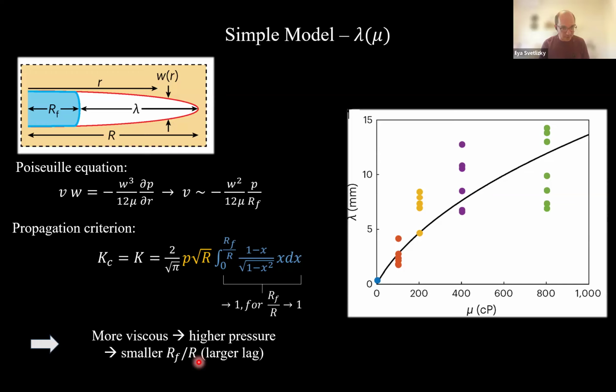This is absolutely right. The answer to that is that I'm cheating a bit, in the sense that the analysis has been done in a specific region, or in a range of radii. The sample is, I don't remember, something like maybe 10 centimeters. So we focused at the middle with a range of a couple of centimeters. Don't go too far away, and so the length of the crack is important. So in the analysis, the radius comes in explicitly. In order to compare all these results, the only way to rescale everything is if R doesn't change much. This is the answer to that.